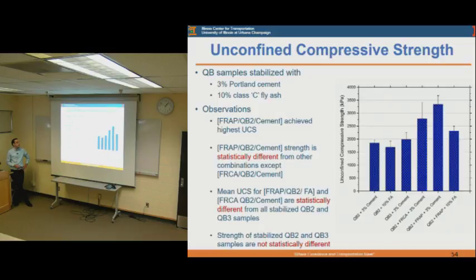Also, in the lab, we investigated the unconfined compressive strength of the different combinations of materials. So in total, there were 6 different combinations of materials that we investigated and then built in the field. And as you see, the highest 2 of these were when we have the quarry byproduct mixed with another recycled material, RCA or RAP, and then cement stabilized. And the ratio of the blending was 70% of QB by weight, and then 30% of RAP or concrete, because we were trying to utilize the highest possible quantity of quarry byproduct in these applications.